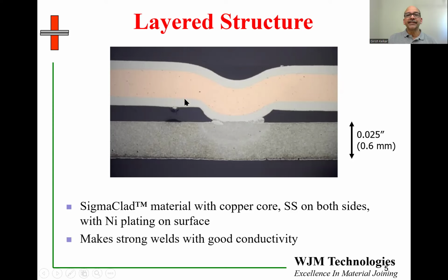During the process, the nickel plating melts and gets squeezed out a little bit, which you can see over here. You can see some elements of fusion on either side, but mostly a solid state bond. And you can also see a heat affected zone over here, which has been produced during welding. So the benefit of these composite tabs is that they are easier for welding because of the stainless steel on the outside. They are good for current carrying capacity because of the copper on the inside, and hence are quite well suited for high power applications such as in EV applications.